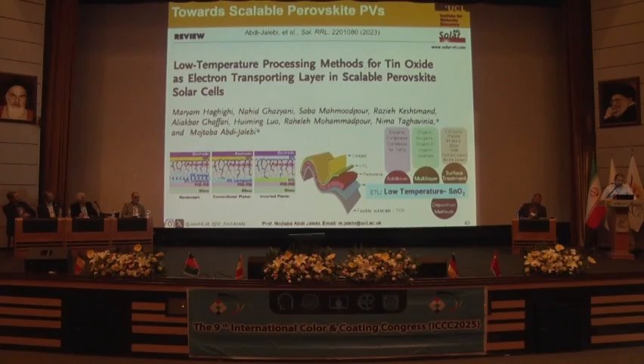Right, the other work we have done is to look at how we can scale up the material in terms of the coating and the deposition. One of the layers which limits the scalability is the electron transport layer. For a solar cell, you need two specific layers: your absorber layer is sandwiched between the electron and hole transport layers. The electron transport layer is the one that normally needs a very high temperature, like over 500 degrees.